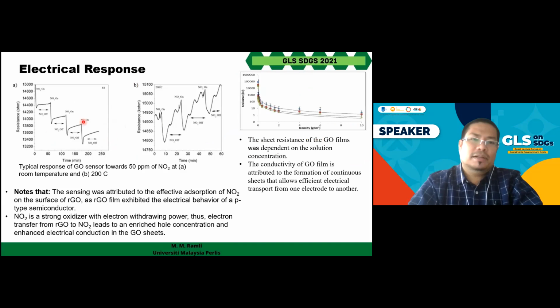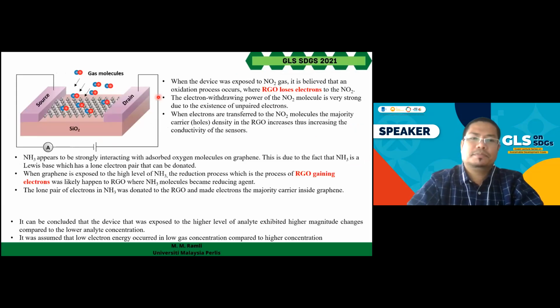So this is a typical response. Basically we measure the response of nitrogen dioxide towards our graphene gas sensor based on the resistance changes. Okay, and then we have tested at room temperature, and we also have tested at 200 degrees C. So this is basically the mechanism of what is happening when you expose our graphene-based gas sensor to nitrogen dioxide, and we also expose our graphene gas sensor to ammonia.